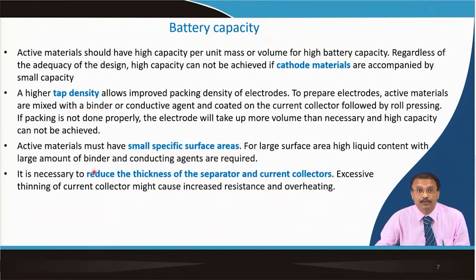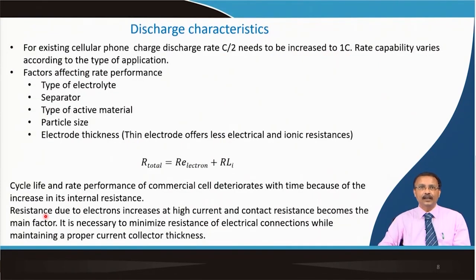It is necessary to reduce the thickness of the separator and current collector. Excessive thinning, if you do of the separator, then if dendrite forms on the graphite, because if you do not match the P by N ratio, then you have lot of lithium, and this lithium will get precipitated on the negative electrode surface, form the dendrite, and if your separator is thin, it will puncture it, and internal short circuit will take place.